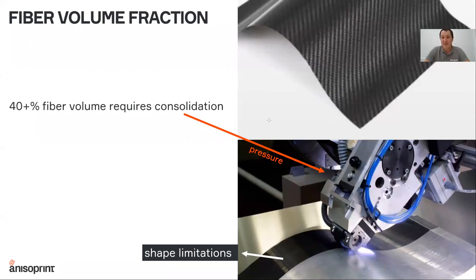As I mentioned before, in this B matrix material, we can reach on average a fiber volume fraction of about 30%, which might sound a bit low compared to traditional autoclave, traditional pre-preg based composites made with the traditional technologies, where you can normally get higher than 40 or up to 60% of fiber volume fraction.